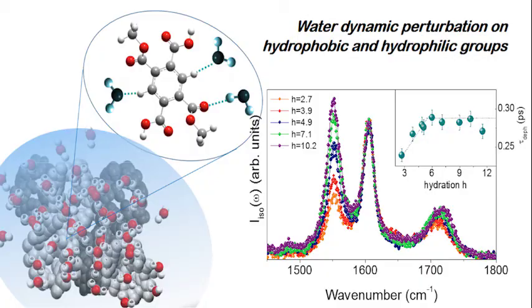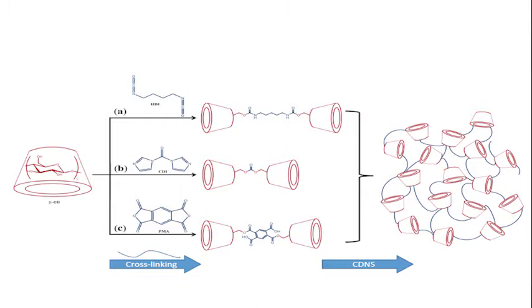So cyclodextrin show quite a good water solubility, but inside the internal surface is hydrophobic. The water insoluble molecule can be allocated inside the cavity, and this gives rise to a complex, which is called an inclusion complex, where the cyclodextrin acts as a host and the other molecule acts as a guest. But there is no chemical bond establishment between the two. So this is what we call a supramolecular complex. This behavior was exploited and it is still used to enhance the solubility of some drugs which are not very water soluble. Cyclodextrin can be used also as a monomer for obtaining polymers, and these kind of polymers are the cyclodextrin nanosponges.